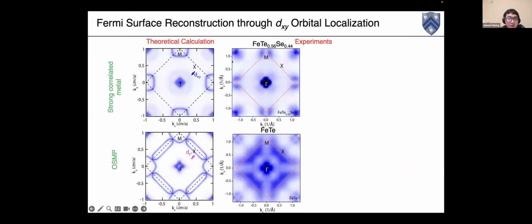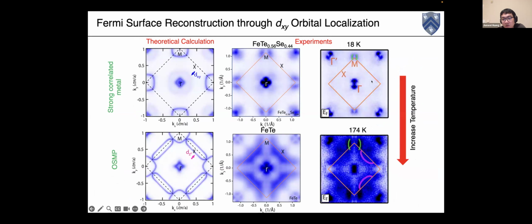And then we can compare the Fermi surface mapping we obtained by the ARPES experiment with these theoretical calculations, and they match pretty well both in the strongly correlated metal phase and this OSMP phase. And we know that when we increase temperature, we can also drive the optimal doped compound into the orbital-selective Mott phase. So we also compare the Fermi surface at the higher temperature. We find that in the high temperature Mott phase, the Fermi surface also matches with the OSMP phase calculations, although the data looks fuzzier.